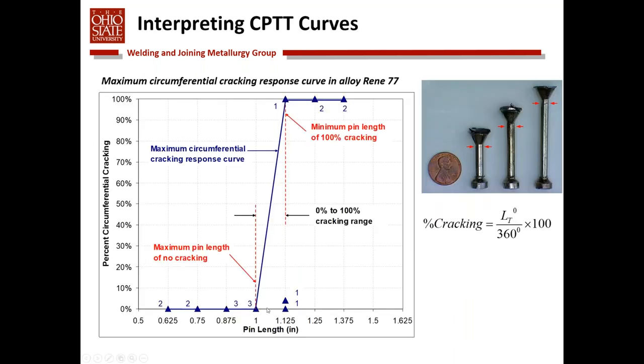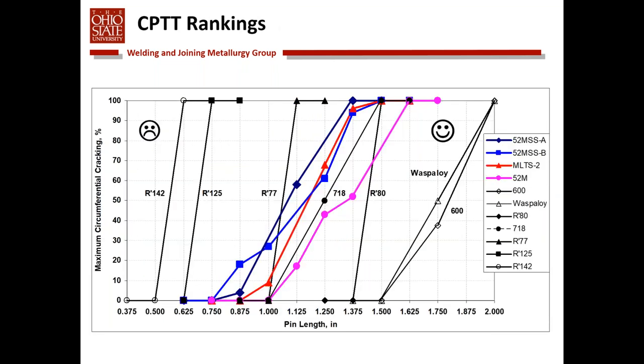The typical data is shown here, where we're looking at pin length versus the circumferential cracking. So the degree of cracking around the entire circumference of the pin. So what happens is we get no cracking, and then in many cases we get a pretty rapid transition at some critical pin length or some critical strain where we get 100% cracking. And again, in many cases, the head of the pin physically breaks off. The red arrows here indicate typically where cracking would occur in these particular pins.